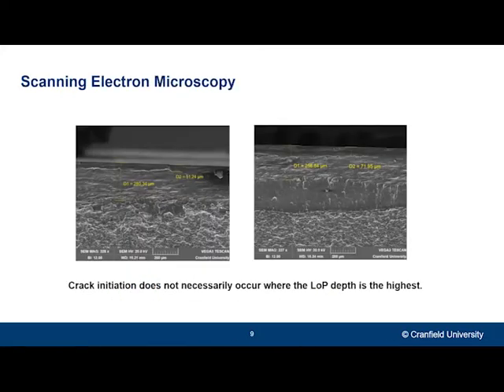So a very interesting finding was when I observed the fracture surfaces using SEM or scanning electron microscopy. And I saw that the cracks on those 400 micrometer defects did not initiate where the depth of the defect was the highest. So this is telling me that the geometry of the defect, say how sharp or how blunt the defect may be, is having a predominant effect on the failure of the joint. So failure is influenced not only by the depth of the defect, but after a certain critical depth, it's the geometry of the defect that's playing the dominant role. And this is something that we'll be studying further in the future for this project.